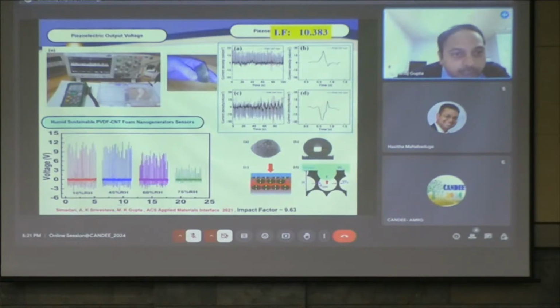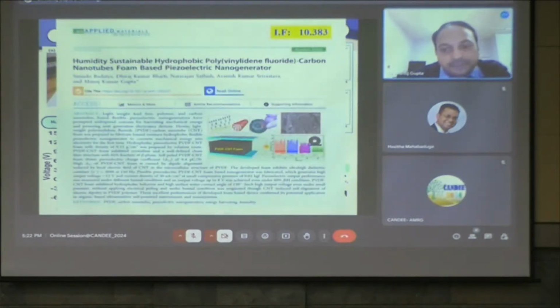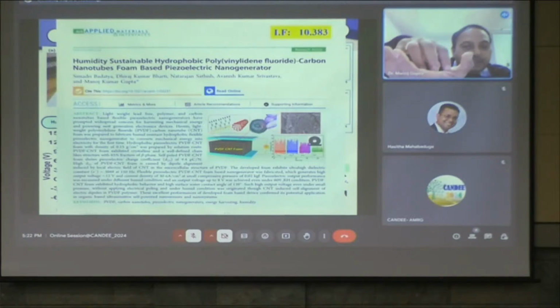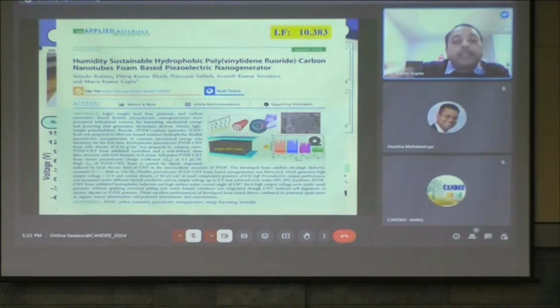Now, here we set up an experimental plant where we created humid conditions, different relative humidity conditions, and we measured the output voltage up to 75% relative humidity. You see, even up to 60%, the output voltage was stable, about 9 volts. And this is just because of the hydrophobic nature of the PVDF. So in raining conditions also, the pressure coming from the raindrop will be able to create electricity, and the raindrop will not damage the performance of the nanogenerator.